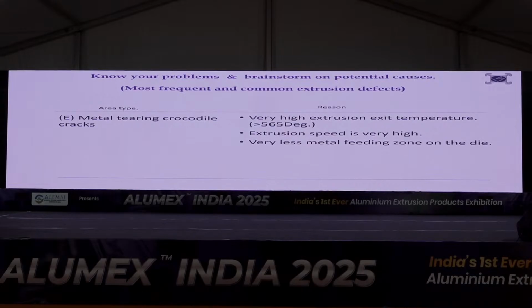Next comes metal tearing or crocodile cracks. In common language in our country, everybody says shearing, shearing, shearing. No one knows what shearing is. They think that the material is not bonding, so they just say shearing. Shearing can be there only and only due to crossing beyond the incipient temperature level, which is around 80-85% of the basic metal melting temperature. If we apply 70 to 72% of the basic melting temperature, it goes to the plastic state. But the moment it crosses 80-85%, it reaches the incipient melting stage and the metal becomes a bit brittle. It tends to lose its malleability.